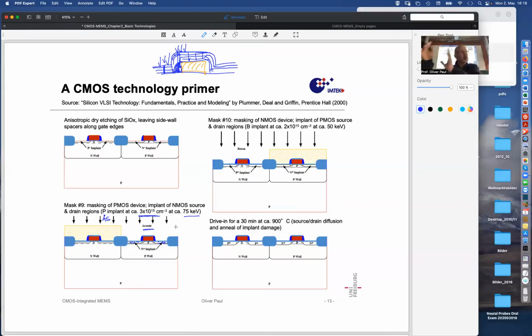And then of course during the subsequent history that has some temperatures, these dopants are redistributed at an intermediate temperature for a short period of time. And that means that this big concentration redistributes over a few hundred nanometers of thickness, maybe a micron, maybe half a micron.